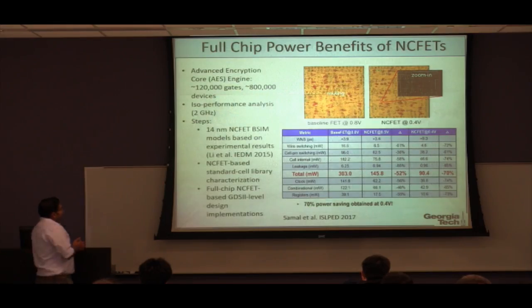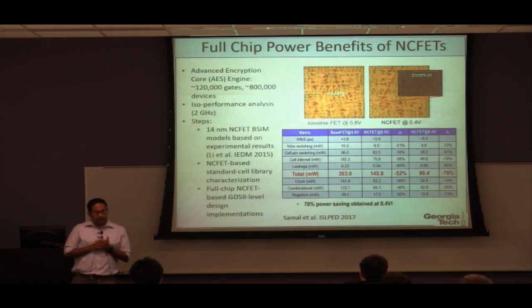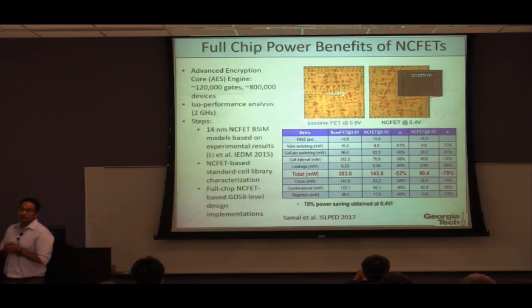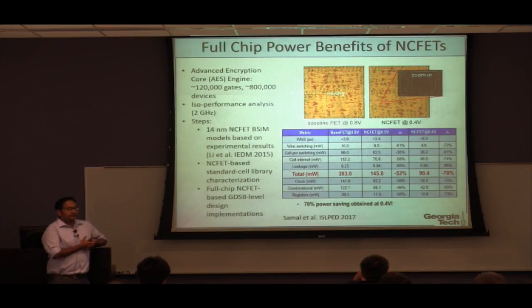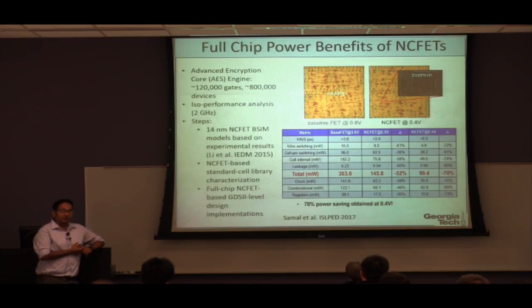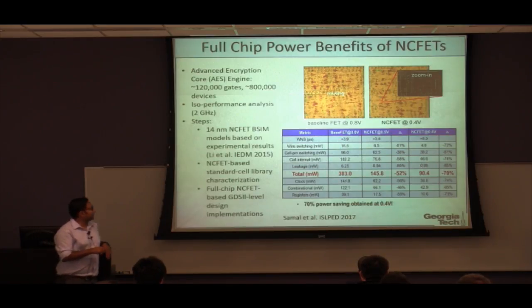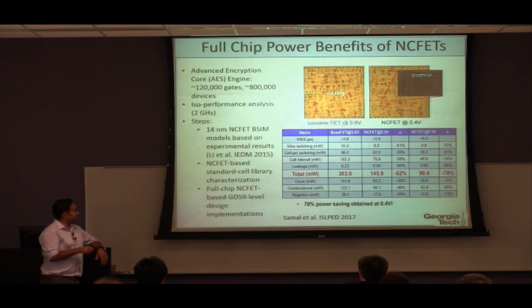So going beyond that, we collaborated with Professor Sung-Kyu Lim at Georgia Tech, and we did a full chip analysis using this NC FET technology. So we used an advanced encryption core engine, which has close to a million devices. And with this model, what we could show is that the same chip without negative capacitance runs at 0.8 volts at 2 gigahertz.